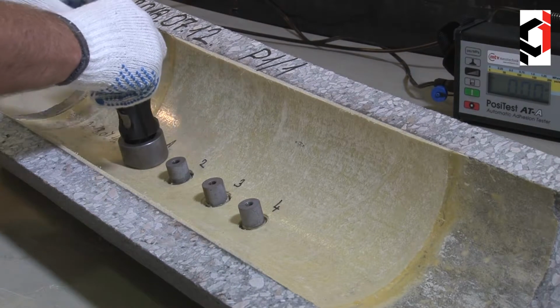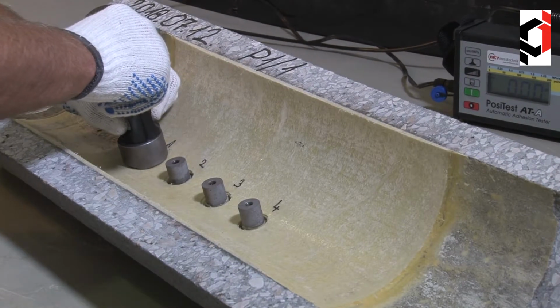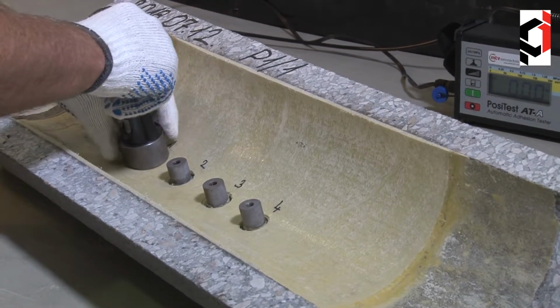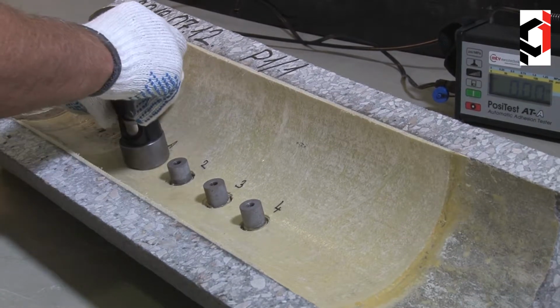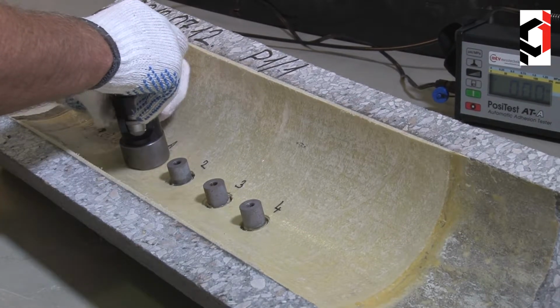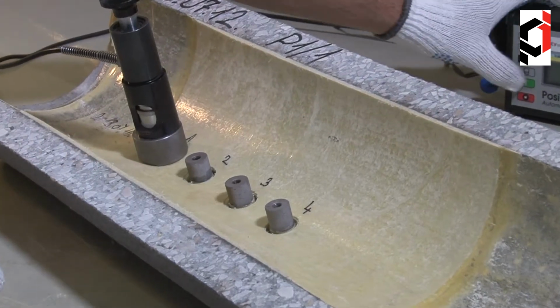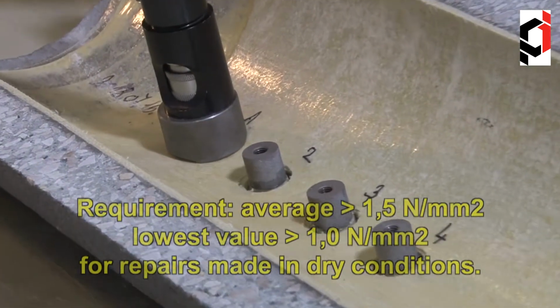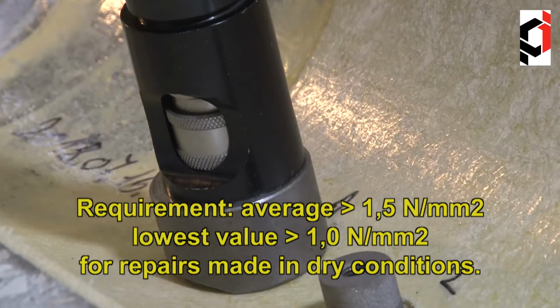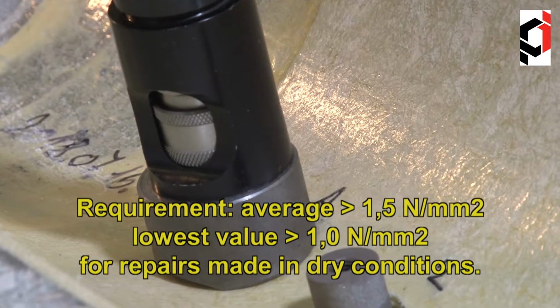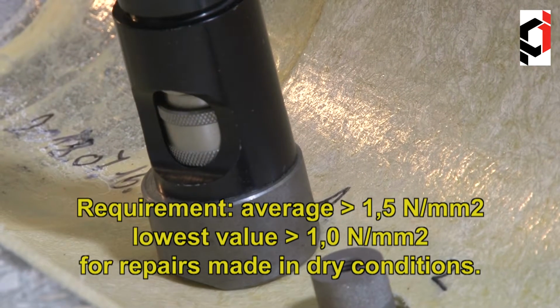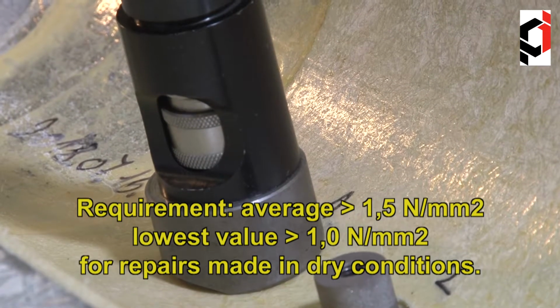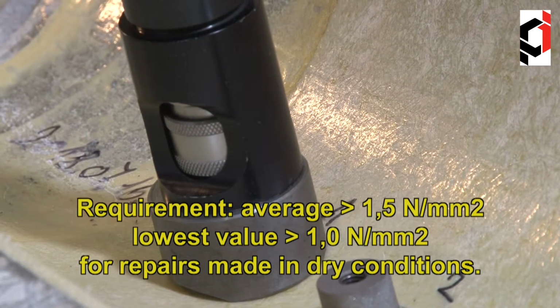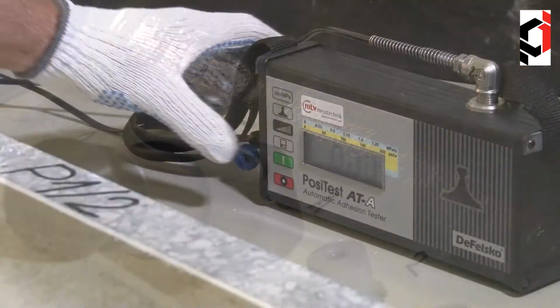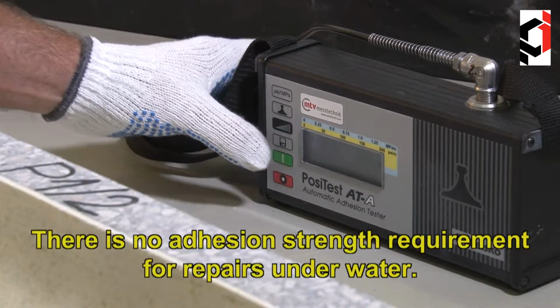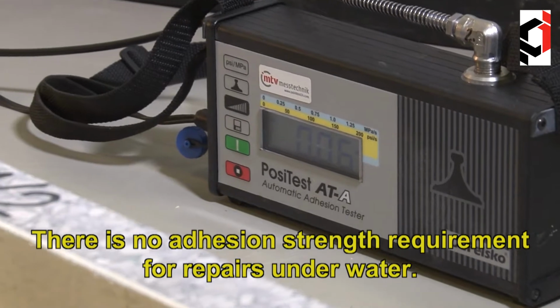The test method is the same for the specimens made in dry conditions and underwater. The pull-off test is carried out by a calibrated, displacement-controlled DEFELSKO PosiTest adhesion tester. According to the European regulations, the average value shall be at least 1.5 megapascal and the measured lowest value at least 1 megapascal. There is no standard adhesion requirement for repair underwater.